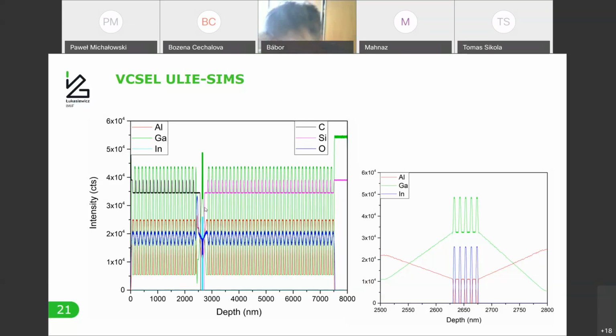May I? So you use the same ion gun for that, and you are changing the angle of sputtering, or you have some additional? This is the same. Everything here is done with the cesium gun. So you are changing the angle during the analysis. Yes, right. I'm changing the incident angle, and what's even more funny, I'm also changing the polarity during the analysis. The software I'm using does not really allow to do it, but with simple scripts, you can do it. You can automate it.